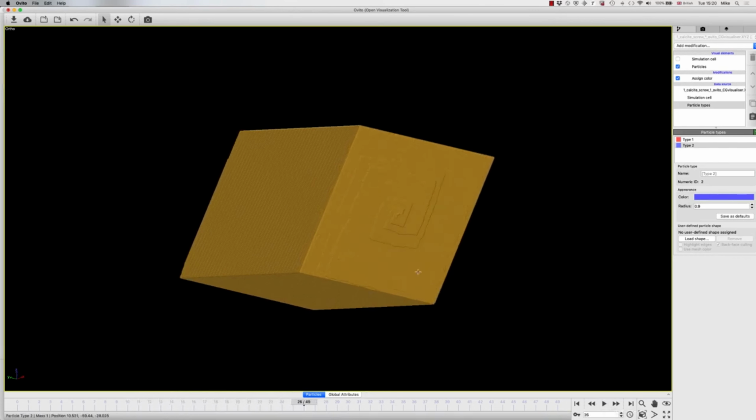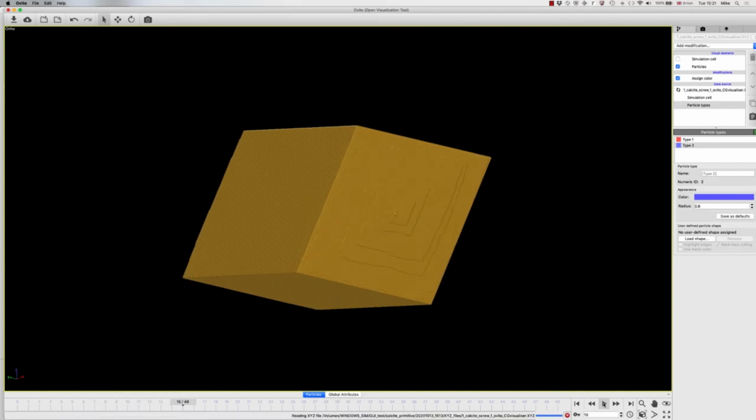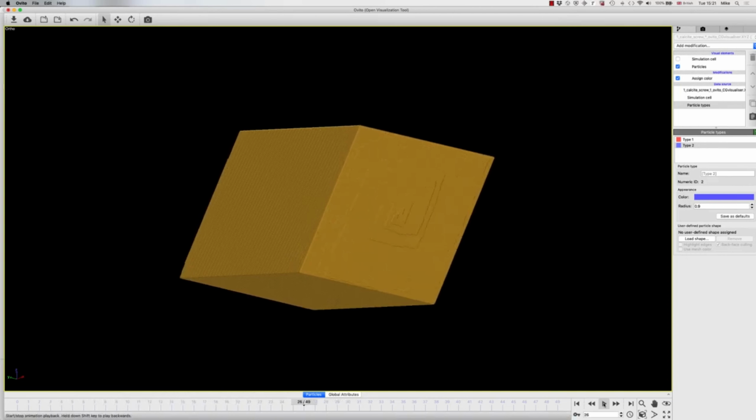And what we see in this particular case, for this particular screw running this direction, we actually have a double screw core because the Burgers vector permits a double terrace to emanate from the screw core. But we've used exactly the same seed crystal in order to do this particular calculation.